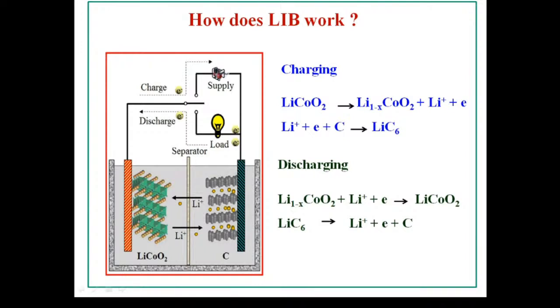So what happens during the charging process? You see the lower arrow: the lithium atoms come out from the lithium cobalt oxide and go to the graphite, sitting in between the interspacing, and a separator is given so that the cathode and anode do not touch each other. You can see that delithiated Li(1-x)CoO2 forms. It means some lithium has gone out from the cathode to the graphite side. And when we are using the battery, those lithium which were sent to graphite come back to their original home, and they find it very comfortable there.